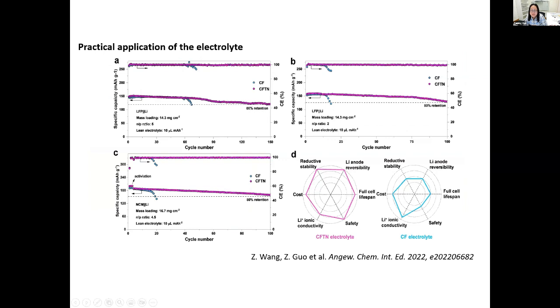And then we tested the full cell in this electrolyte, using lithium iron phosphate as the cathode and lithium metal as the anode. The mass loading for the lithium iron phosphate is quite high, 14.3 milligrams per square centimeter, with lean electrolyte. The cell can be cycled for 150 cycles with capacity retention of about 80%. And to maximize the energy density, we also used NCM811 as the cathode with a mass loading of 16.7 milligrams per square centimeter. Again, under lean electrolyte conditions, the cell can be cycled for 100 cycles with capacity retention of about 80%. So although the performance is not perfect, remember we did not optimize the cell configuration. This is just a demonstration.